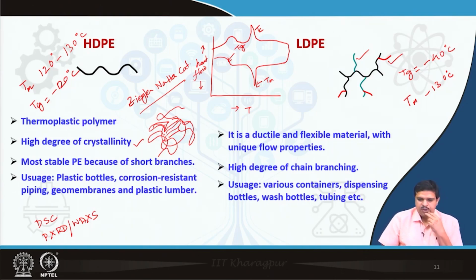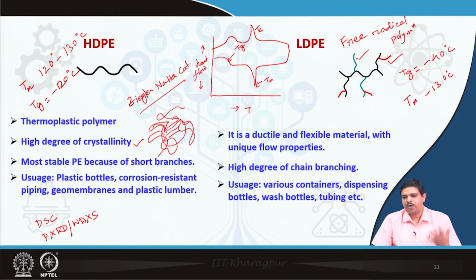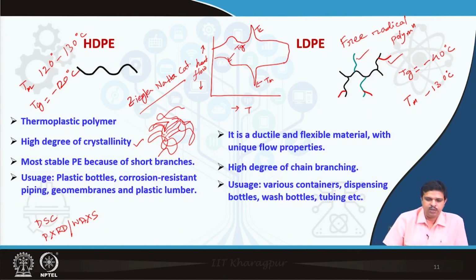So, this is about the low density polyethylene, and obviously it depends on the polymerization protocols. For this one you cannot make it by the Ziegler-Natta catalyst. So, here we generally follow free radical polymerization. Why? The reason is very obvious: for free radical polymerization we do not have any control over the chain length and the branching. So, generally for free radical polymerization we get the LDPE, and for HDPE we have to follow a different polymerization protocol. Fine.